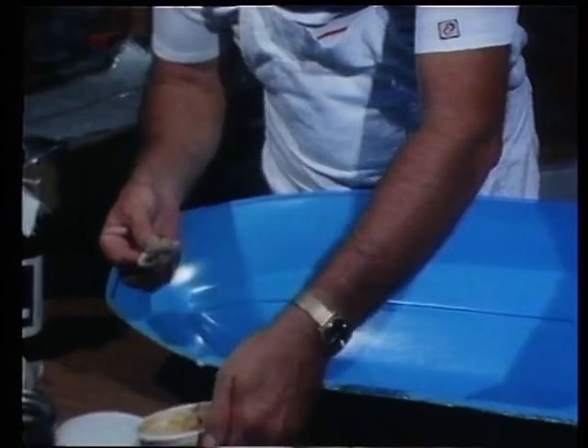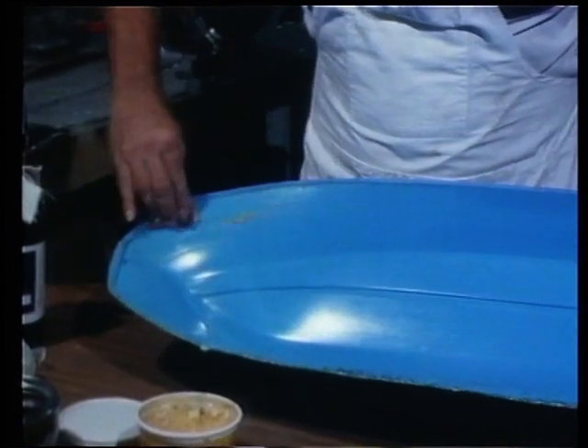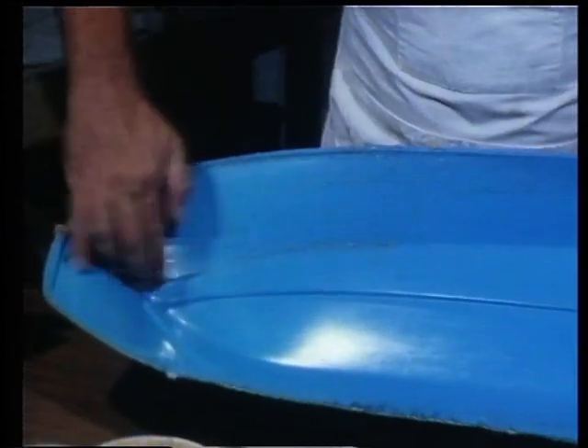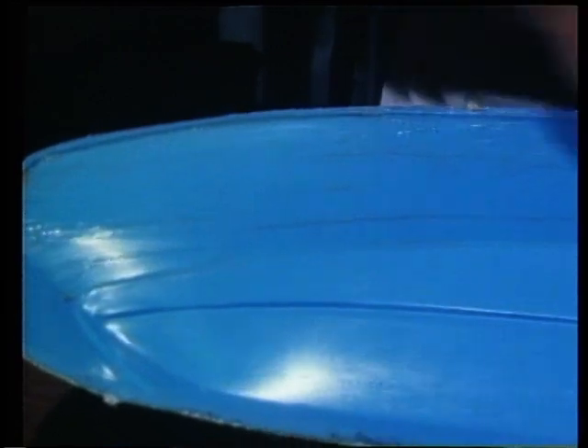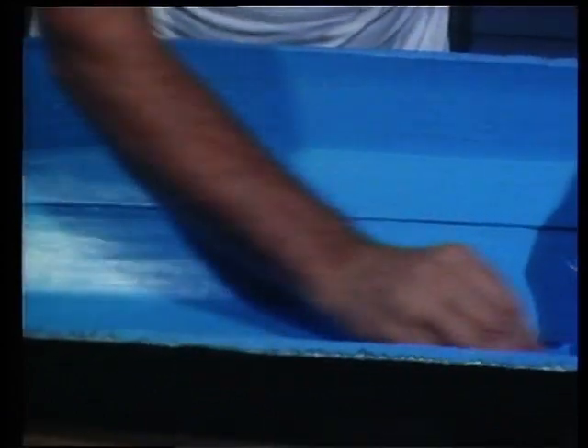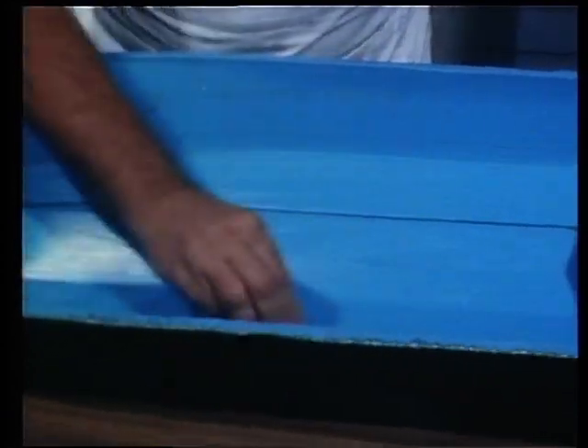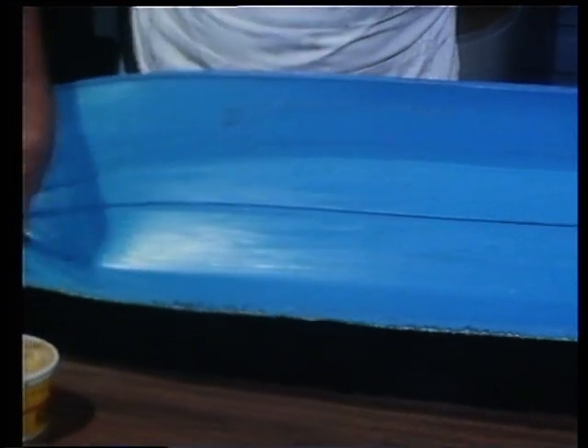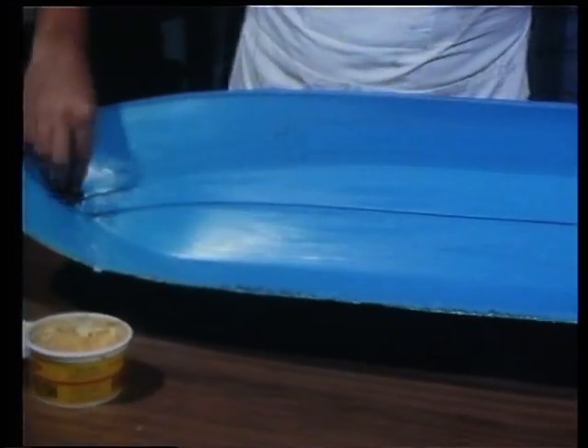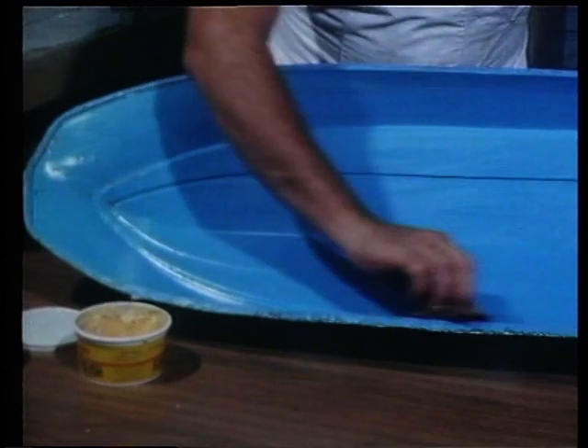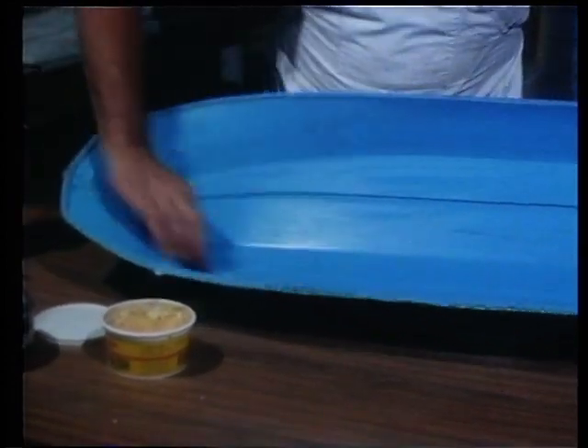Now, in this particular case, it's a two-part release system comprising a non-silicone floor wax which you spread liberally over the inside of the mould, making sure that you don't miss any part of it whatsoever. Just make sure that your wax is smeared evenly over there, and a piece of old rag is ideal for that purpose. Be quite liberal with the wax, just to make absolutely certain, and make sure you get the tip of your finger or your fingernail down into the rag to push the wax down into those little tight contours.